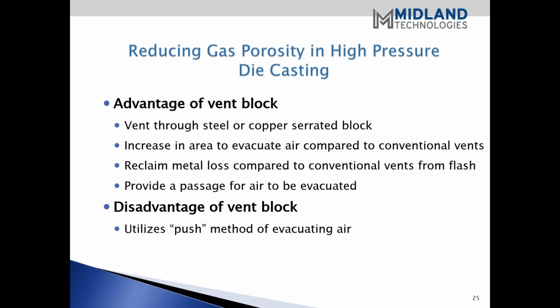It increases the area to evacuate compared to conventional venting. So the area of the block itself can be about 10 times more than what you would get from one conventional vent track. So sometimes in certain cases the real estate needed to put in a vent block is less than using conventional venting. And you also can reclaim the metal lost compared to conventional vents from flash.